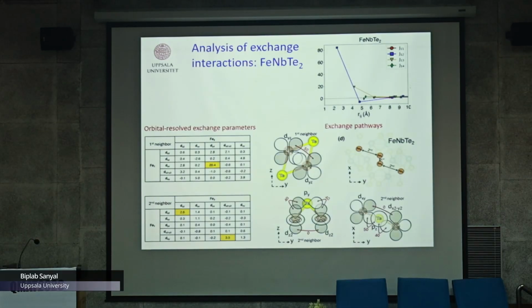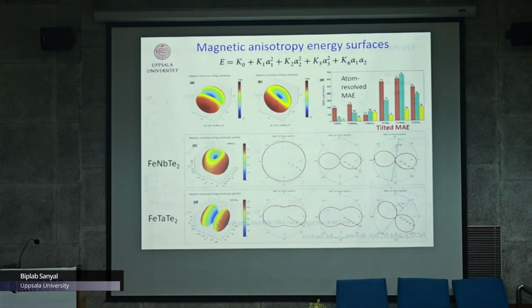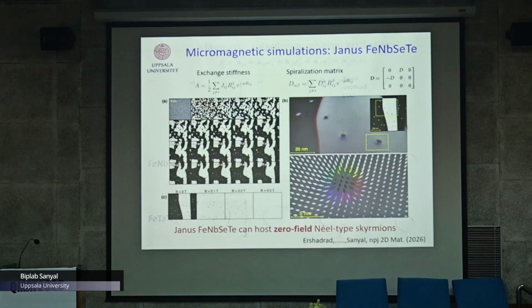And I don't have time to go through this analysis, but you can analyze the exchange interactions through the different types of orbital resolved exchange parameters and the corresponding hopping between different orbitals. This kind of analysis exists here to understand why certain interactions are ferromagnetic and why certain interactions are antiferromagnetic. So I skip this one. Also, another thing emerges here, that the easy axis of magnetic anisotropy is a tilted one. So this is another feature of this kind of magnets. Both for iron niobium telluride and iron tantalum telluride, we see some kind of tilted magnetic anisotropy feature, which can be interesting for some experimentalists actually.